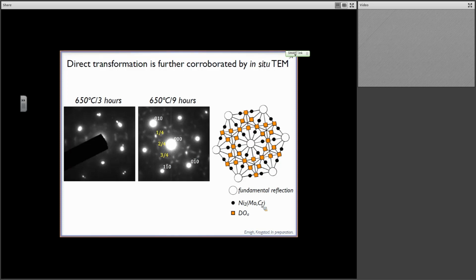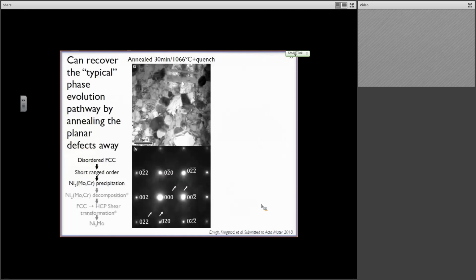Okay, so this is all well and good. It's quite interesting. But maybe I just changed everything when I sputter deposited this film, right? So as a sanity check, we did an anneal on the microstructure. We took the thin film, that columnar thin film, and heated it up to 1066C, which is the industrial spec for this particular alloy. For 30 minutes, we quenched it, and we got rid of the nanotwins. We got rid of the texture.